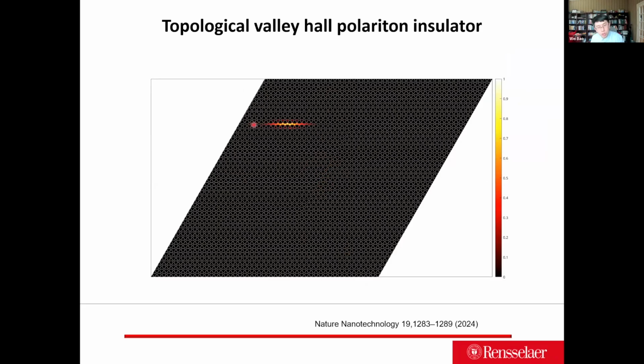So for the edge mode, they can propagate without loss. Essentially, anything that stays in the edge, because there's a bandgap, there's no allowed bulk mode. So only the edge mode is allowed there. So once you see something propagate against the sharp turn, that's the edge mode. That's smoking gun proof. Side evidence is they show G1 coherence.